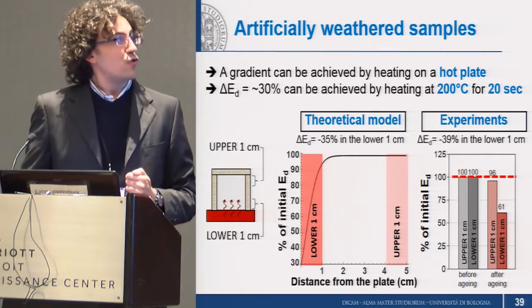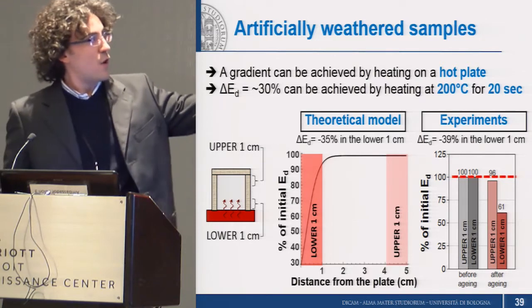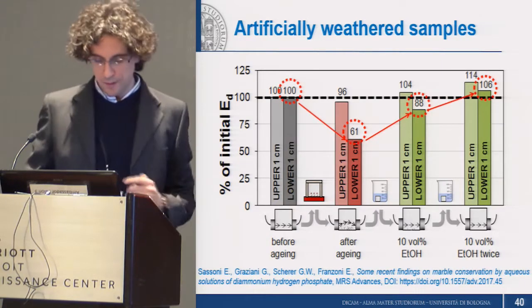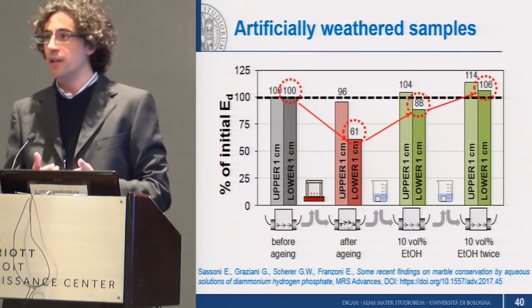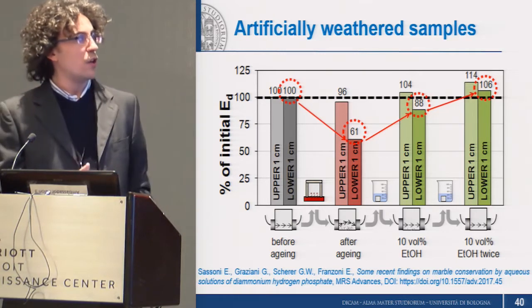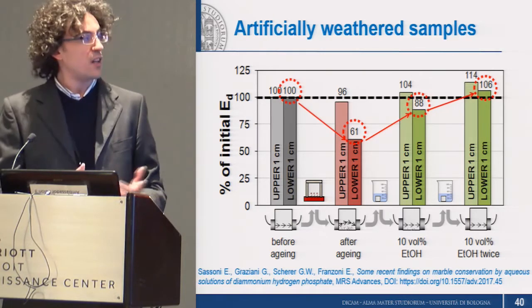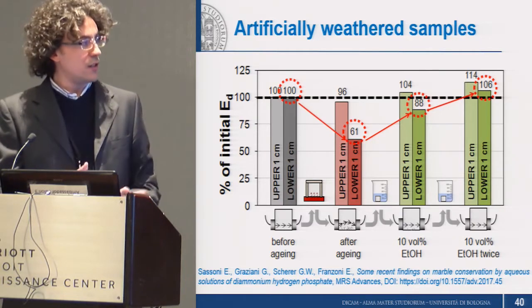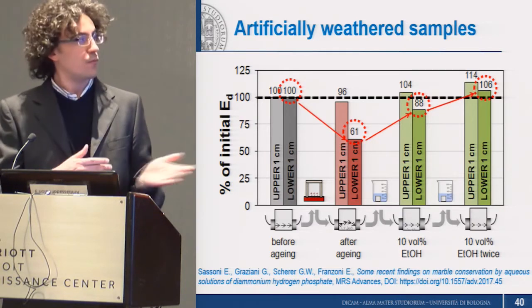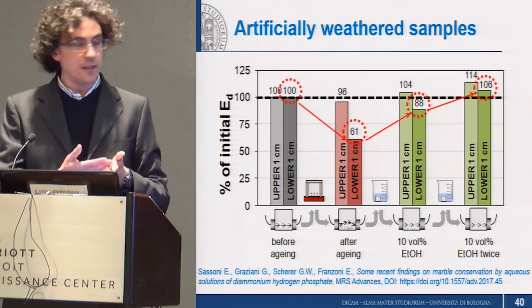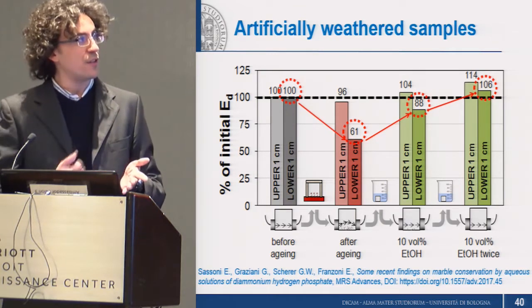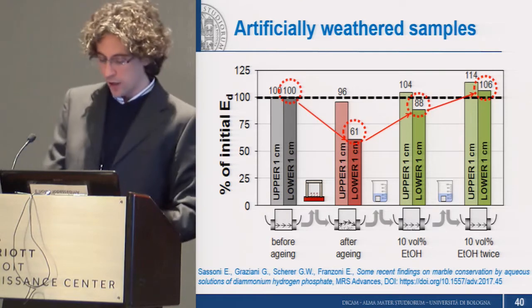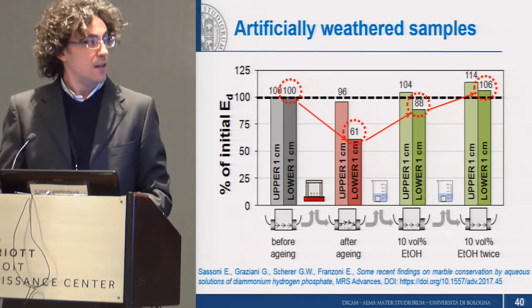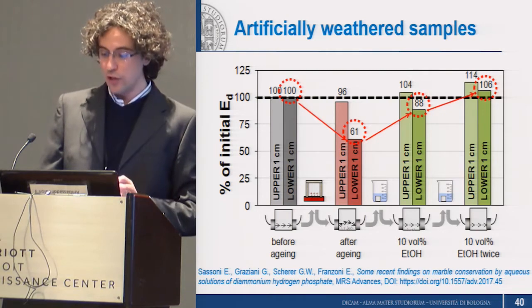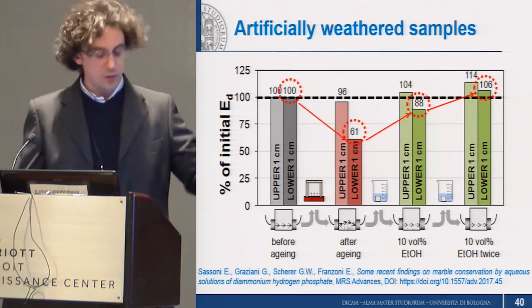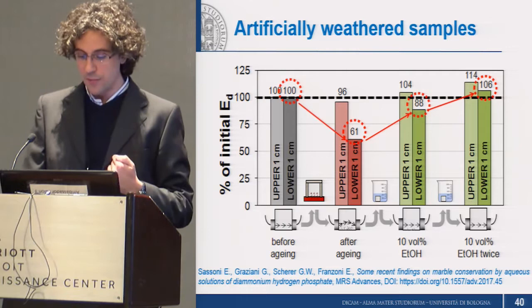So then we tested our treatment, and as you can see, starting from undamaged marble, we first carried out our own artificial deterioration, and we got a 39% decrease in dynamic elastic modulus. And then by treating our stone, we got a significant improvement in mechanical properties, and after the second treatment, we basically got the mechanical properties completely restored to the original condition, and also, importantly, without causing over-consolidation of the sound part.